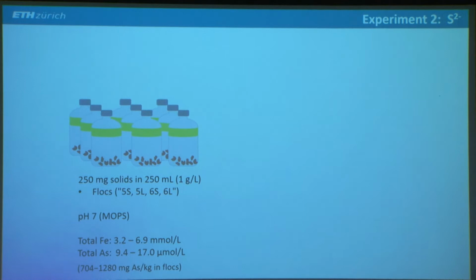So let's see what happened here. We did a similar experiment. This time we used 1 gram per liter solid concentration. We had 4 different flocks for this experiment. It was all done at pH 7. We spiked sulfide at 2.5 millimolar. It's actually a fairly high concentration, I must admit.